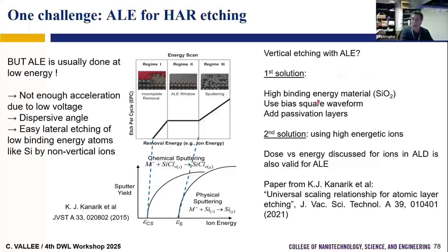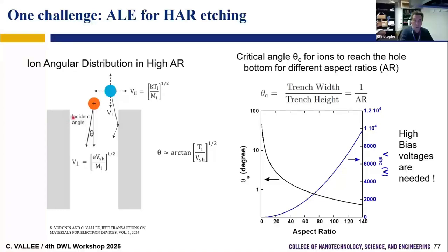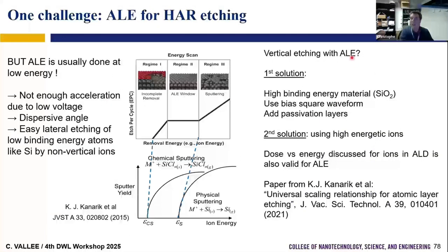Because for the ALE process, remember, we have a low energy where we want to be between two sputtering threshold energies. But if we have a low energy, we have a huge angle of dispersion. So it means that no energetic ions will come to the bottom in high aspect ratio. So ALE cannot be used for high aspect ratio etching. But we have some solutions.